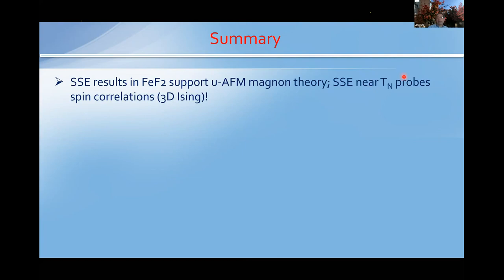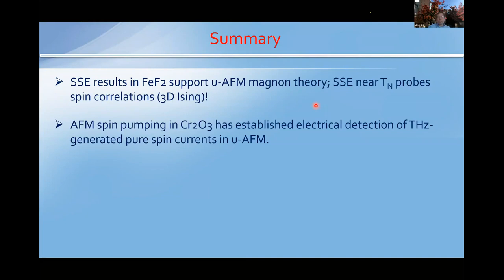At the Néel temperature, or the transition temperature, we have this pronounced fluctuation. This is related to universal critical phenomena. But what we learn is that from spin Seebeck, we probe not the order parameter directly, but rather the correlation of spin fluctuation. Using antiferromagnet spin pumping, we can generate the resonance. I forgot to mention earlier, in antiferromagnetic resonance, typically you need to go to much higher frequency to excite such a resonance, so it's not as easy as ferromagnetic spin pumping. But we demonstrated very clearly that this is actually the spin current generated.